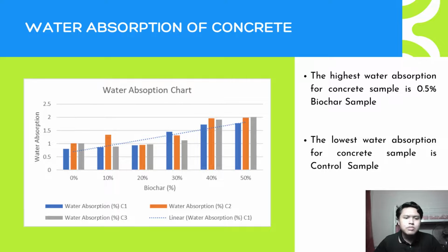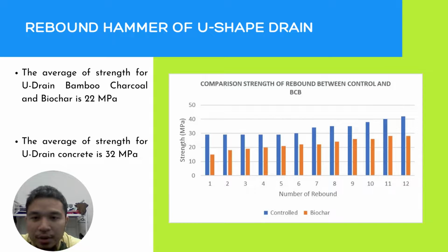Other than that, based on the chart, we can see the percentage of water absorption increases as the amount of biochar increases. Therefore, we will use 10% biochar, because it is almost similar to the control concrete. And this is the graph for the rebound hammer test of the U-shaped drain. As we can see, the average strength of lightweight concrete is quite comparable to standard concrete: lightweight concrete has 22 megapascals and standard concrete has 32 megapascals.